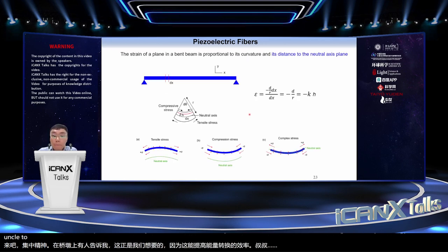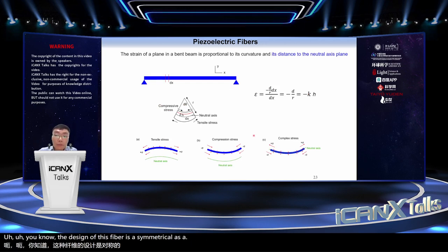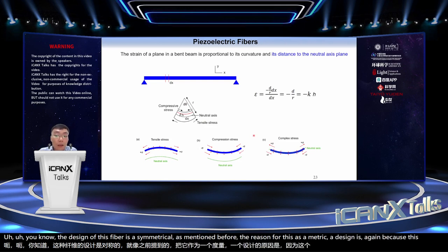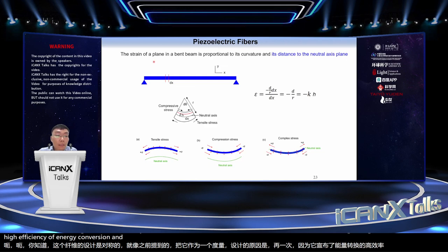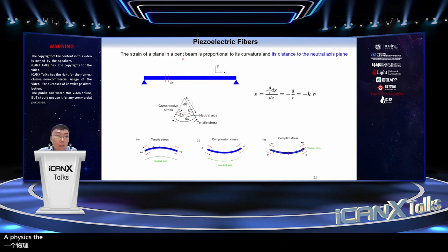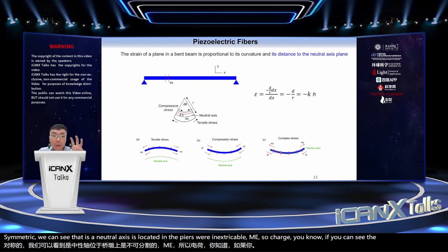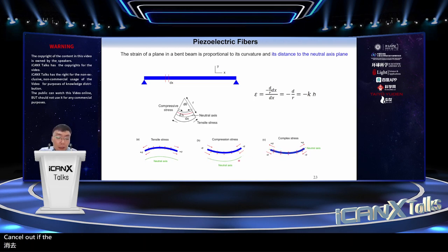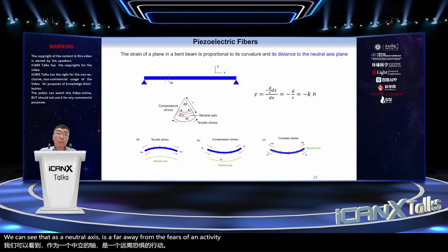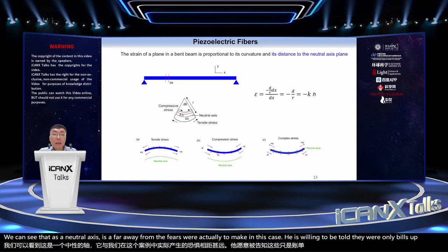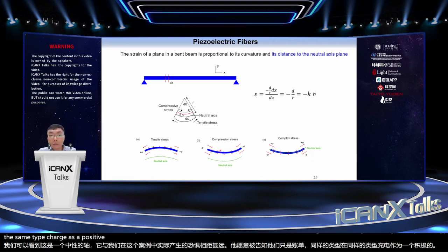And number two, the design of this fiber is asymmetric, as I mentioned before. The reason for this asymmetric design is, again, that it allows a high efficiency of energy conversion. From the physics, the strain of a plane in a bendable beam is proportional to its curvature and its distance to the neutral axis plane. If the fiber design is symmetric, the neutral axis is located in the piezoelectric domain, so the charges will be canceled out. If the fiber design is asymmetric, the neutral axis is far away from the piezoelectric domain. In this case, the piezoelectric domain will only build up the same type of charge, either positive or negative.